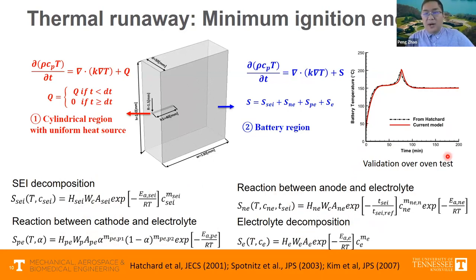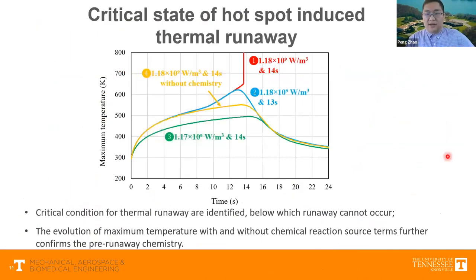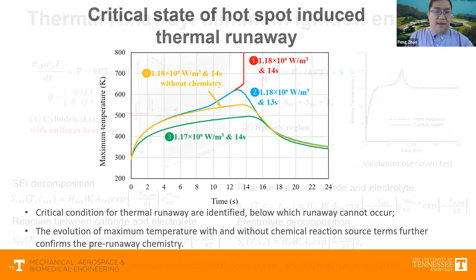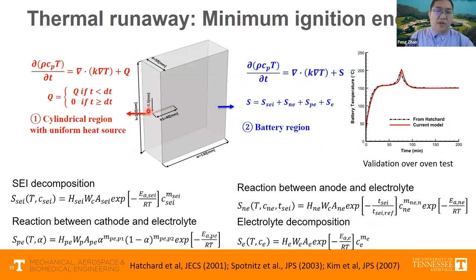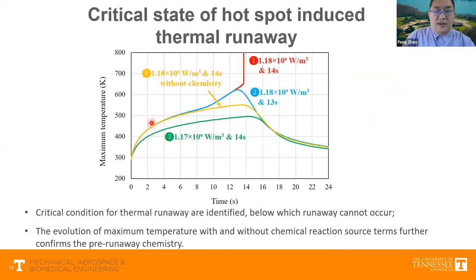So we're using the models of the lithium cobalt oxide to do some simulations based on the configuration we have. What we do is basically we are changing different heat source intensity and duration in this cylindrical region to see if we can trigger some runaway. As you can see here in case one, with this particular heat source intensity and duration time, thermal runaway is successfully triggered. Starting from this point, by either reducing the heat source intensity or the duration time, we're not going to have thermal runaway, as seen in this green curve and this blue curve.